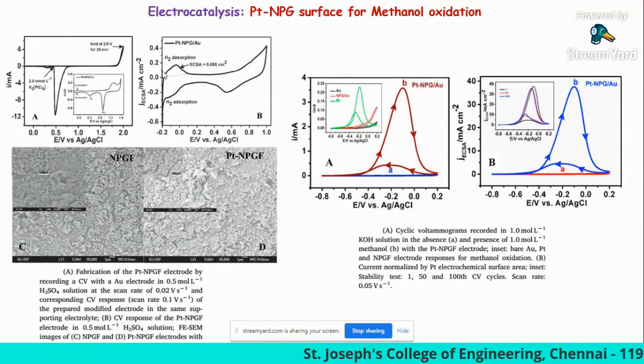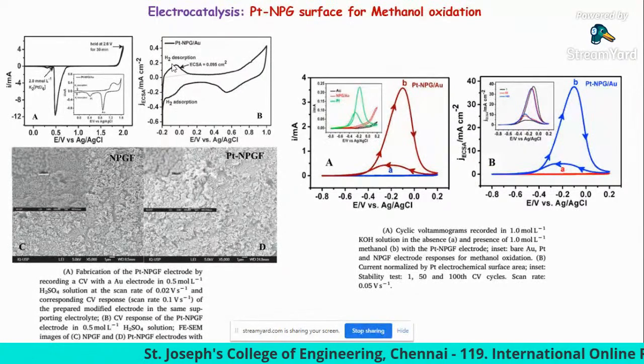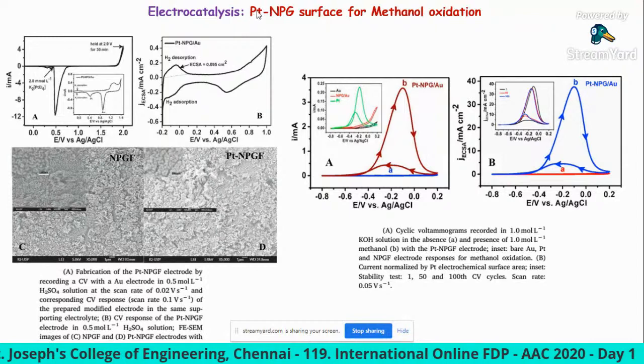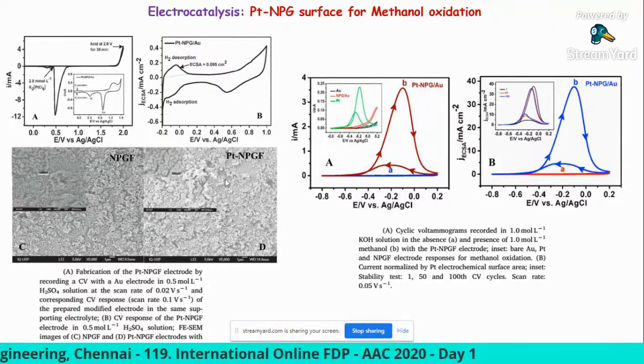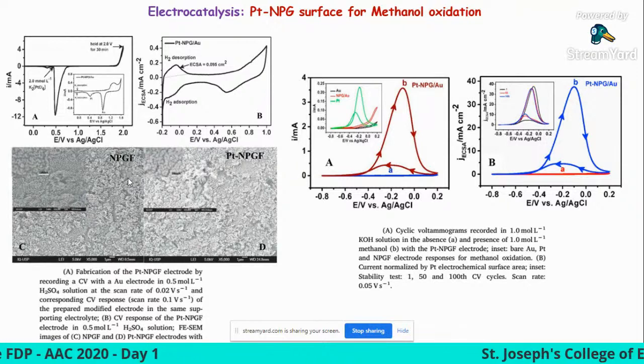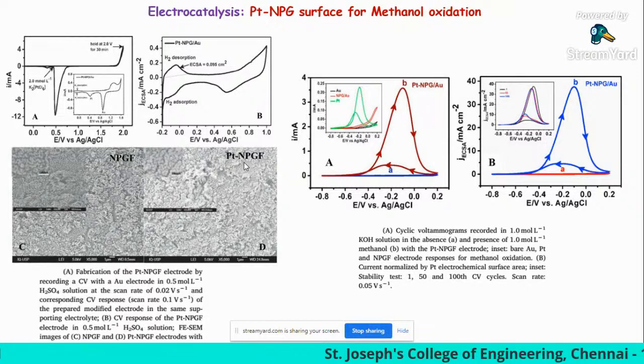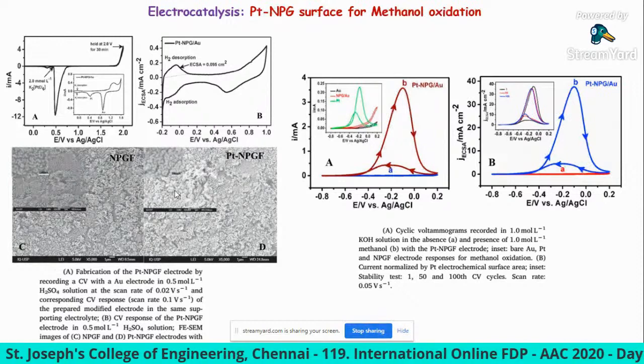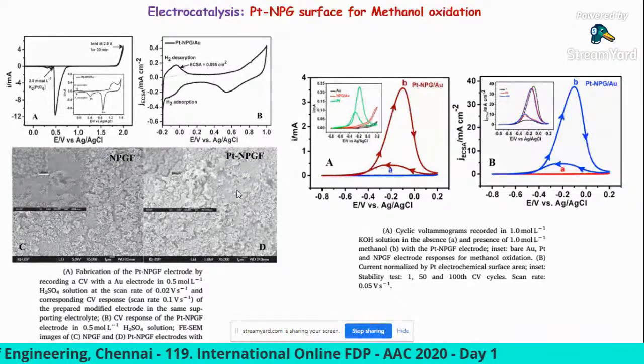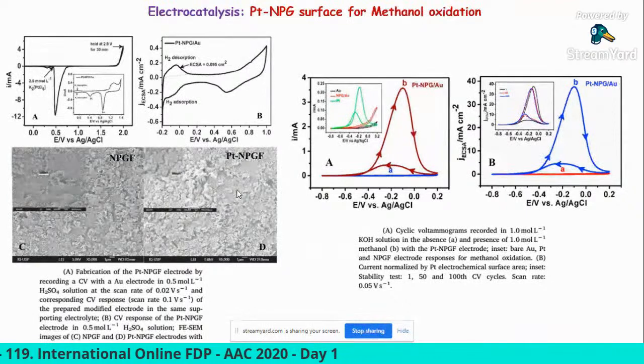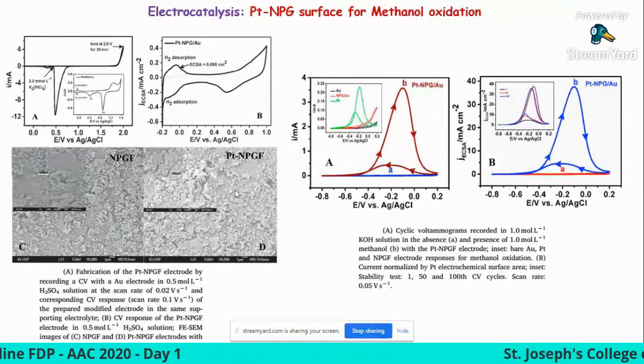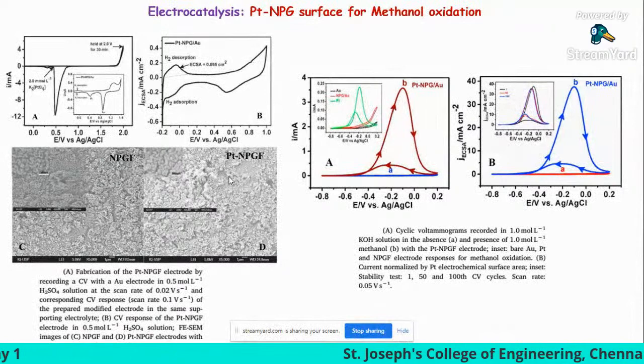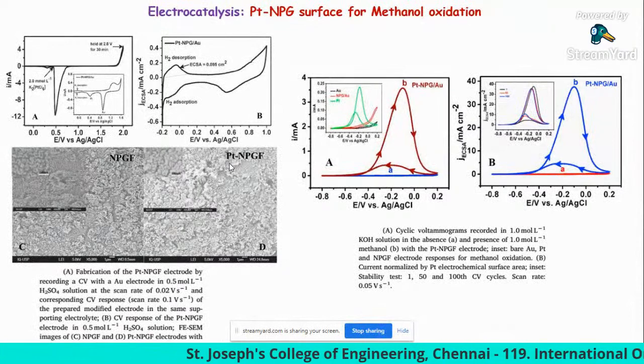You cannot get this kind of behavior from a gold electrode. So this clearly indicates that the Pt was present on the nanoporous gold structure. This is the corresponding scanning electron microscopic images of nanoporous gold and Pt-decorated nanoporous gold electrode, where there is not much difference between the two. However, the energy dispersive EDX analysis shows there was 2% of Pt present on the surface.